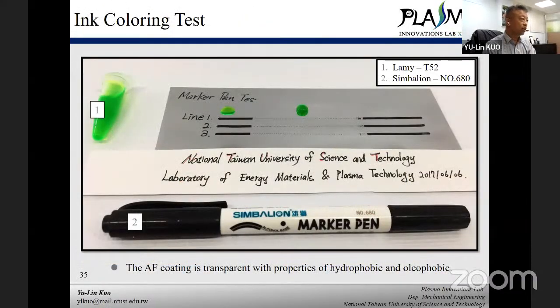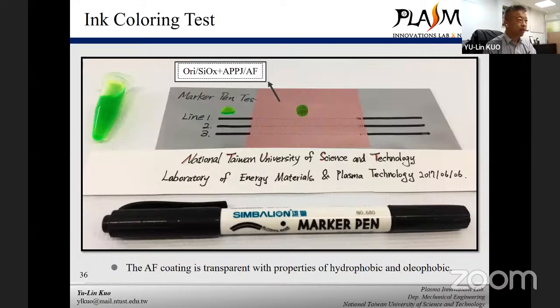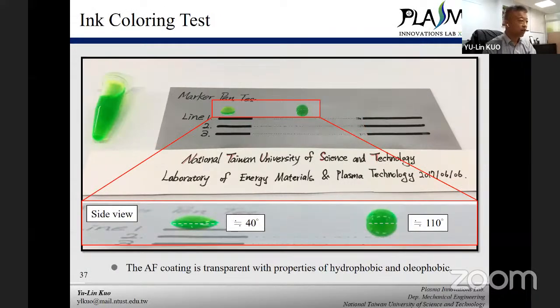So we try to use some ink coloring to see the difference. As you can see, these are the treatment areas. We can see the water-based ink with a contact angle of around 40, which means the wettability is very high. However, the treated area has a contact angle around 110, which means it will not be easy to contaminate the surface of the object.